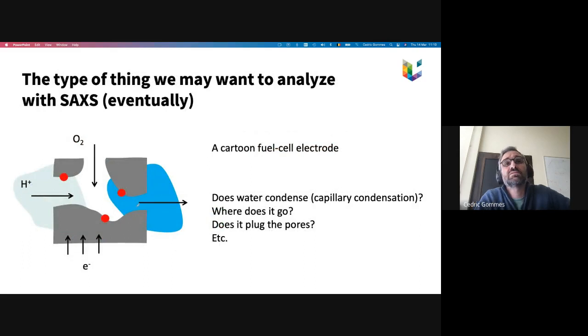So, yes, the type of thing that you might want to analyze with small angle scattering, and I say eventually because this comes with some major challenges, is typically what would happen, for instance, in fuel cell electrodes. This would be a porous, typically porous carbon, because it has to be electrically conductive. So you have a pore that would be, say, 10 nanometers across. You have metallic nanoparticles used as catalysts. You have a proton conducting membrane that brings protons in, oxygen that flows in, and then typically this reaction creates water. And a question that you may want to ask is, where does the water condense,